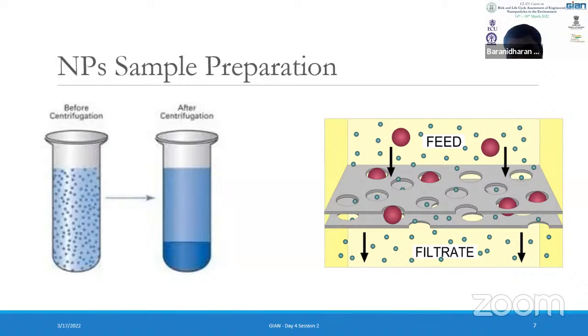With respect to the filtration technique, normally 0.45 micron or less, such as 0.22 micron, filters are used to separate out the nanoparticles from the solution, because that is the most commonly used in the research community; 0.22 and 0.45 are the commonly used filter media. Though 0.45 micron filters are no longer efficient to distinguish the dissolved solids from the particulate fractions, serial filtrations are kept in place in combination with ultrafiltration, so that the dissolved species can be removed, and then the nanoparticle can be successfully quantified and characterized.